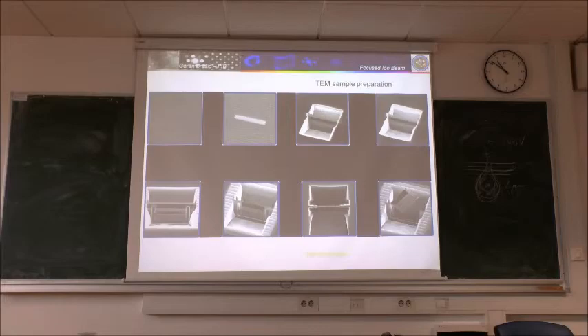And as the last example, where focused ion beams could be very useful is transmission electron microscope sample preparation. Those of you that are dealing with transmission electron microscope know how important it is to get good, nice samples. Without a sample, you can do nothing. And nowadays the problem is to prepare a sample at a specific area. It's practically impossible because you are using techniques with which you are within plus or minus a few millimeters, but if you want to exactly make a sample from this part or some other part, you can use FIB. Okay, I can show you a movie, and it's better.